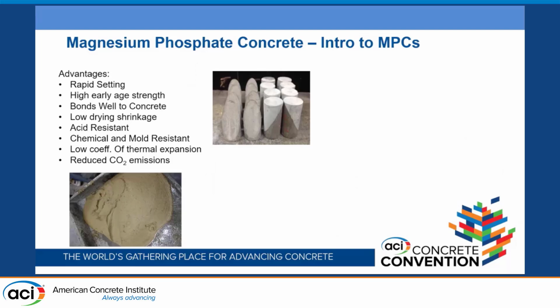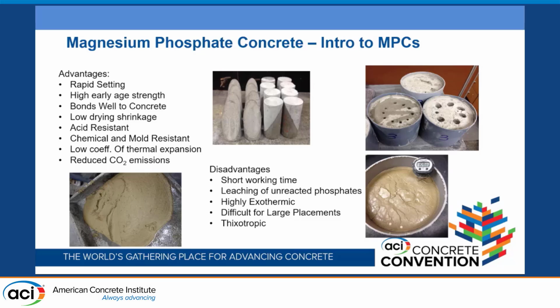So advantages: rapid setting, which could also be a disadvantage, but high early age strength, bonds well to existing concrete, low drying shrinkage, acid resistance, chemical and mold resistance. It's got a low coefficient of thermal expansion and reduced CO2 emissions. Disadvantages: rapid setting. It's a whole balancing act when you're designing these materials. The phosphates are highly, highly, highly water soluble. So if you have any unreacted phosphates in your system and water gets into it, you can actually leach those phosphates out and leave voids, and you have porous concrete.